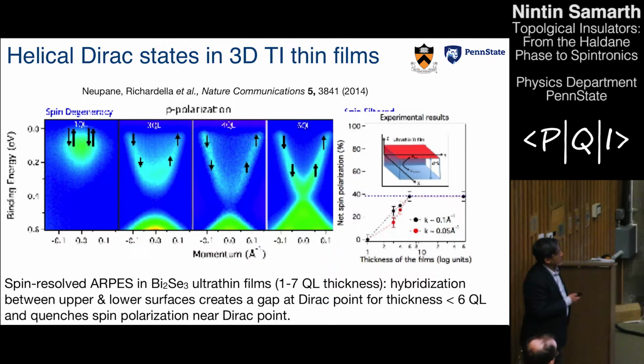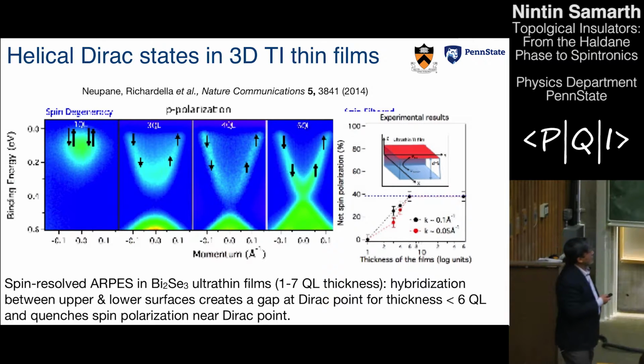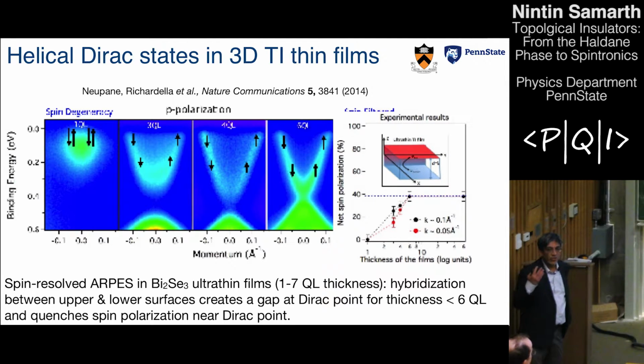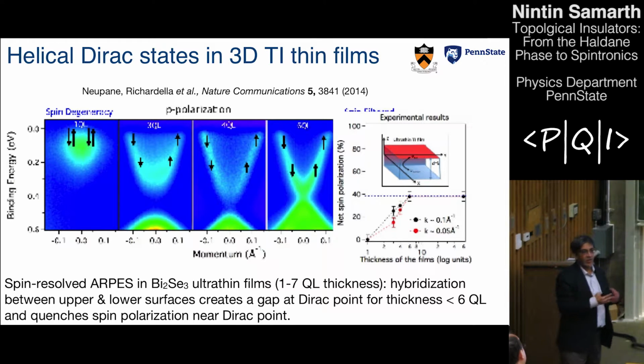We've also done measurements, using samples like this, of the spin polarization by using the Mott spin detector. And what Zahid and his students and us were able to do is to map out how the net spin polarization varies as a function of the thickness of the films. And it's very interesting that you can do this sort of tabletop quantum mechanics, Dirac physics, by using equations that are effectively the relativistic Dirac equations describing these energy states, and map out everything, how the wave functions behave, how the spin polarization behaves. And what you find is that as you open up a gap, as you hybridize the top and bottom surfaces, you start quenching the spin polarization in these samples.